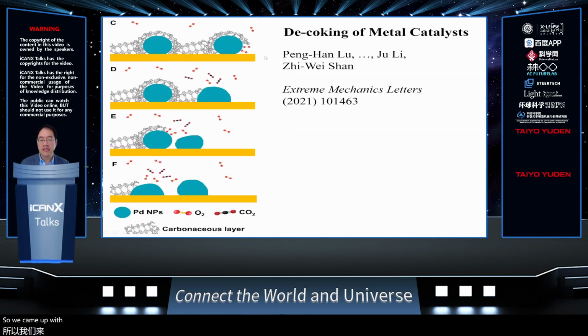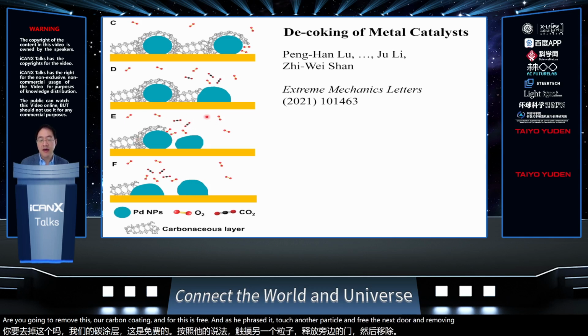So we came up with an explanation of this effect, which is that initially, all these palladium nanoparticles are covered by carbon. This can happen in highly reducing environments in, let's say, the petrochemical industry, where the carbon seals off the contact between the catalyst and the gas, and so it's inactive. But there is always one particle which has some flaws, and in this case, the nanoparticle will be able to react with the oxygen gas, emit carbon dioxide, and remove this carbon coating. And so this is free, and as it frees, it touches another particle and frees the next particle, removing carbon dioxide or carbon monoxide.